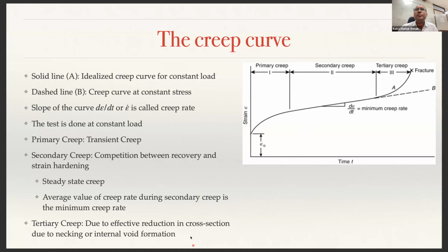And the tertiary creep, because of the effective reduction in cross-sectional area, suddenly you will have void nucleation and then sudden failure that takes place after a long period of time. And typically this is called creep rupture strain, at which creep rupture happens, and the time for rupture. So this is very important to see how many hours I can operate a particular component at such high temperature.